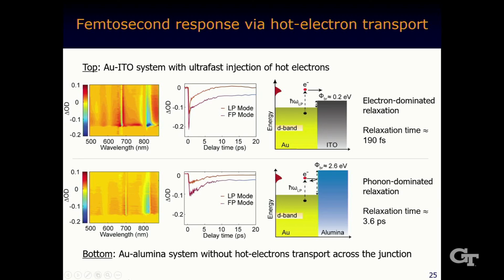So now we do the vertical cutting and see how the change in the optical behavior would be sensitive to the time delay. And you can see that in the gold ITO system with hot electron generation and transport, the modulation is very large. If you translate this delta OD back to the reflection, the change is more than 80%. It happens within no more than 200 femtoseconds, and then it gradually recovers. That's a very fast component, which is related to hot electron transport, and a slow component, which is related to the electron-phonon interaction inside the metal, because hot electrons are generated in the gold. A portion of them can escape from the gold and enter ITO very fast, in a very small time window. And then the rest experience a very slow process.